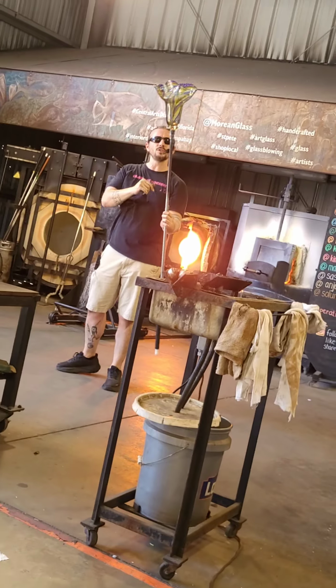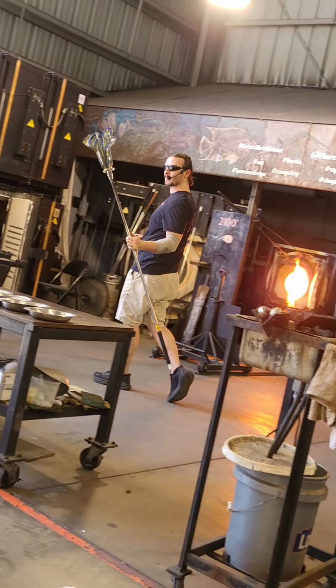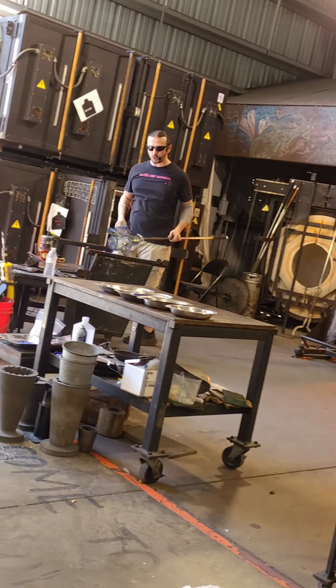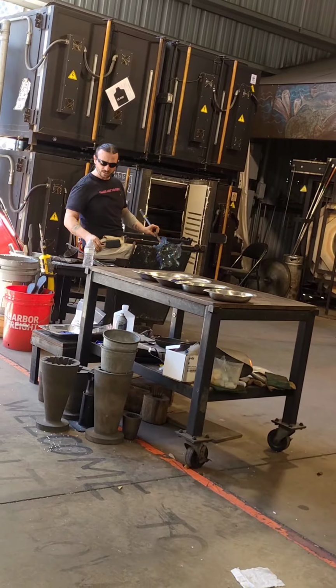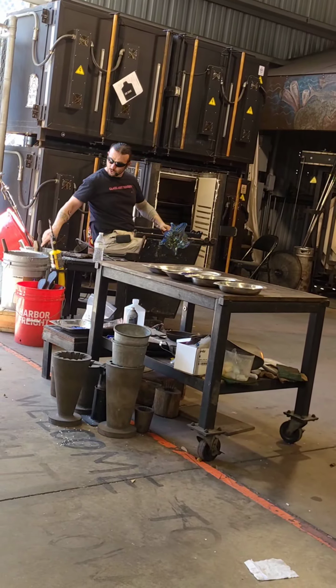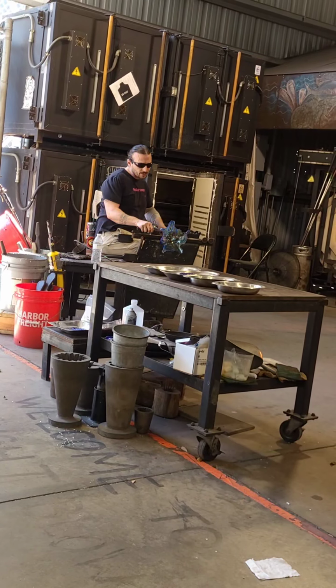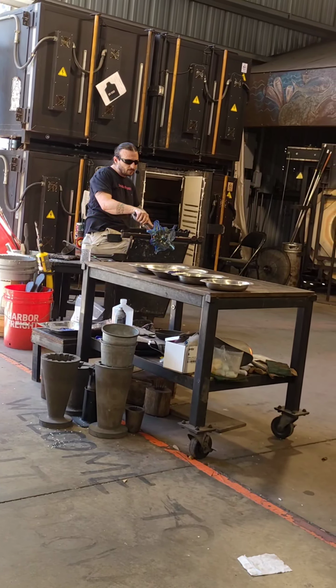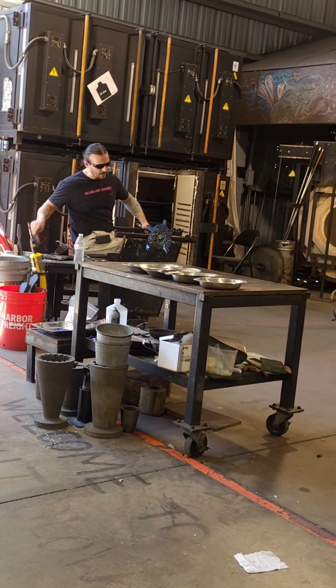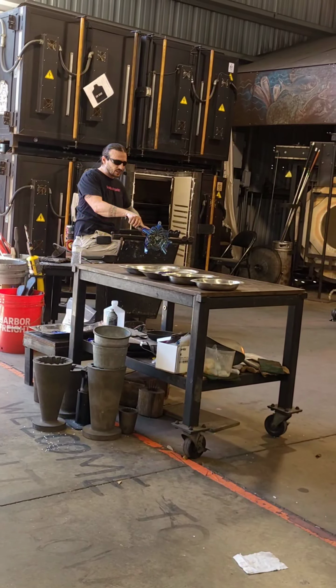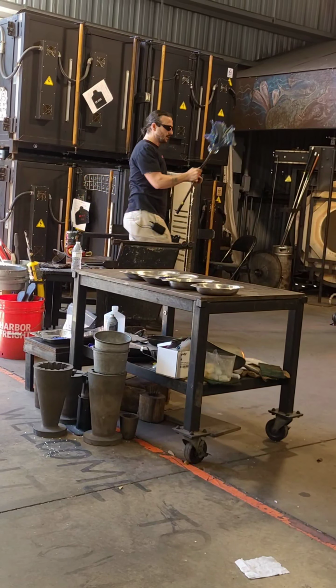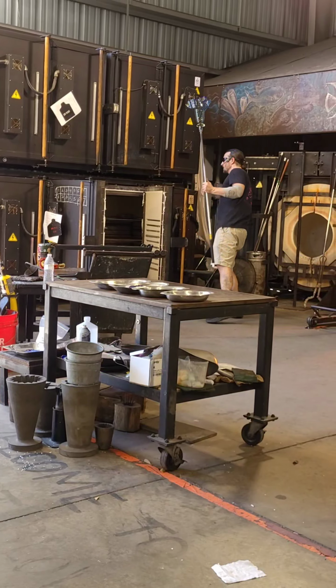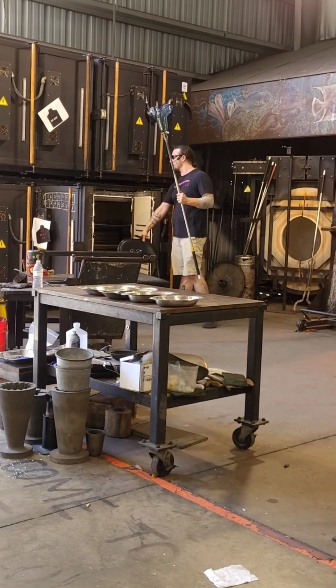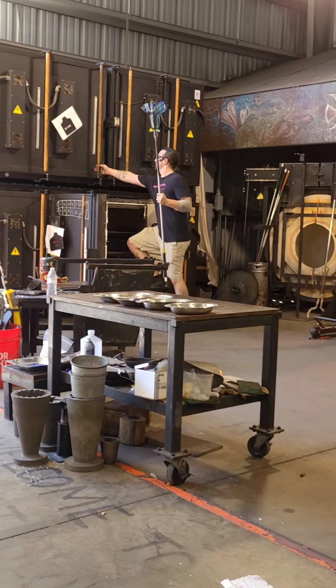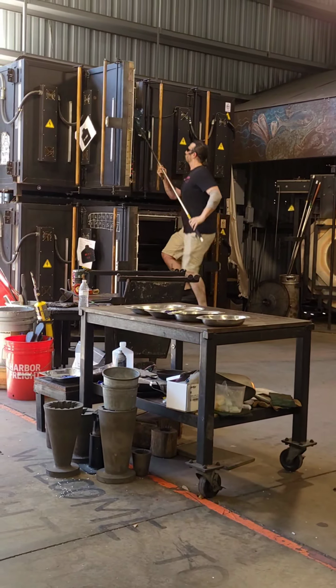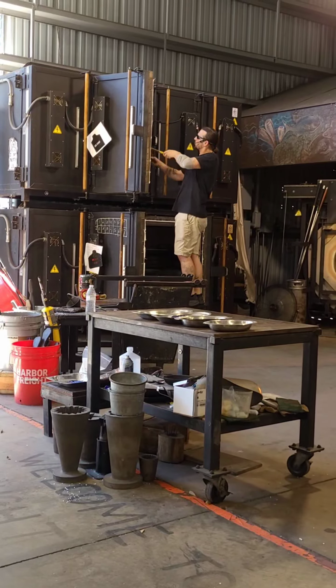Maybe get a look at that fluted top base that I've been making. But now I've got to let this glass cool down very slowly overnight tonight. If it cools too quickly, it'll shatter and break. So I've got to take this piece off the punty rod and put it away into this big black oven behind me. Now this oven is sitting at 900 degrees Fahrenheit. The glass will go into here at that temperature and cool down slowly over 12 hours tonight to room temperature. Now this slow 12-hour cool down will remove stress from it so it'll come out in one piece tomorrow.